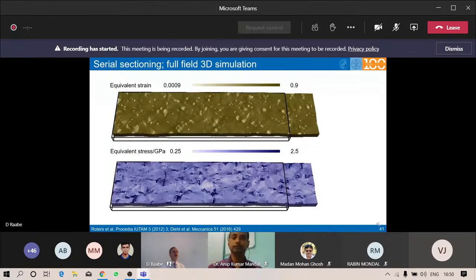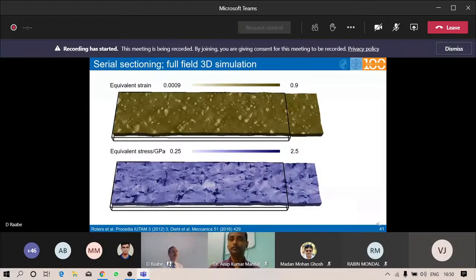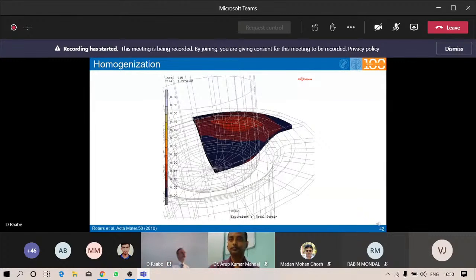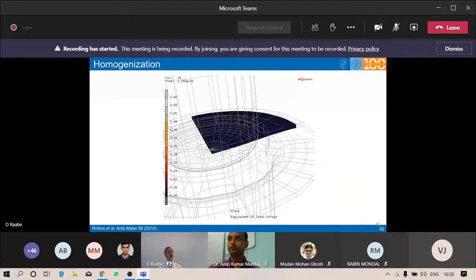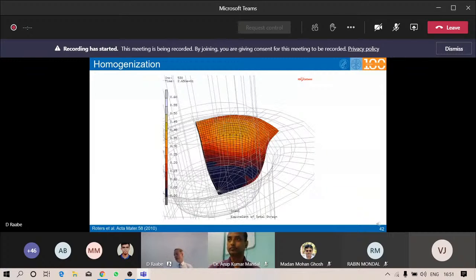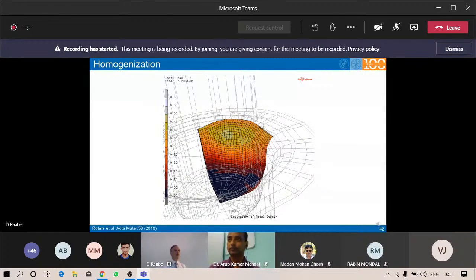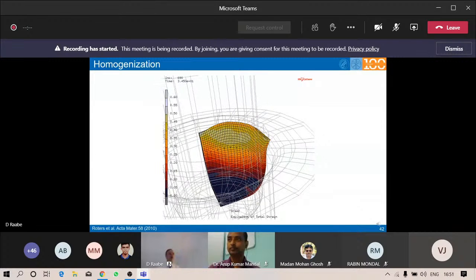And this is not only important for getting a more plausible or more trustworthy result of your simulation, but it's for us very, very important to really test your methods and develop proper models for damage. As I told you, we also use this, jumping out to the other side of the scale end, for homogenized crystal mechanical simulation of larger forming parts, such as done in projects in-house in collaboration with industry for automotive sheet forming, or for the development of advanced yield surface functions. Or we have recently written a couple of papers where we show how you can, on the fly, calculate yield surface parameters from crystal plasticity models.